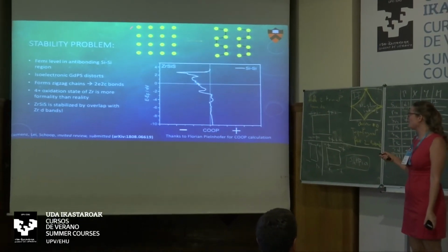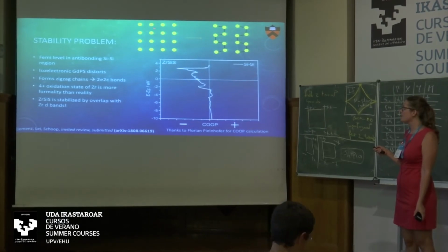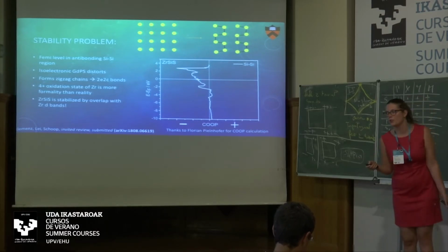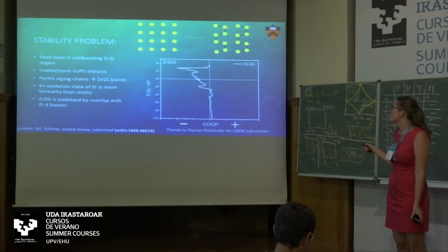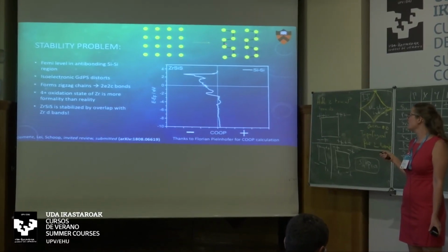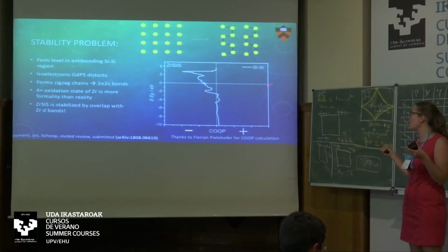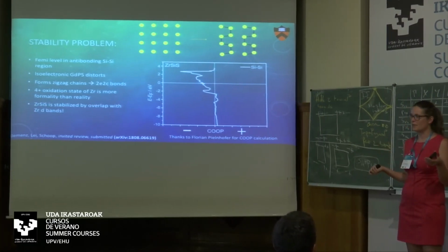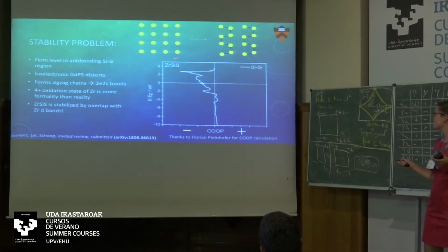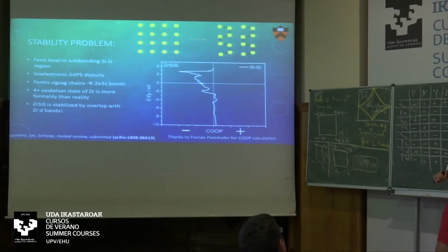So many of these compounds, which are isoelectronic to zirconium silicon sulfide, don't have this square net. They actually distort in these zigzag patterns and are in different structures. And this is actually what you would also imagine from the Zintl concept, because here each silicon has 2 bonds, right, like it's supposed to have. So this is the Peierls distortion that happens to do what chemistry predicts. And even if you look, this is a crystal orbital overlap population curve. Chemists love this.